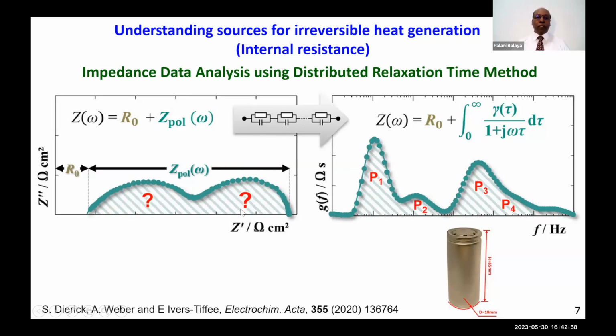But as per our experience over the last 16 years at NUS, we found that there is a certain level of ambiguity in assigning these contributions to the different contributions which I showed in the last slide. So what people do in recent times is the so-called distributed relaxation time. That means they Fourier transform this data and then present this distribution function as a function of the frequency or time. And then you see clearly different contributions. And then we can do additional experiments and attribute these different contributions to different components, which I discussed in my previous slide. So that's what I'm going to show in my next slide.